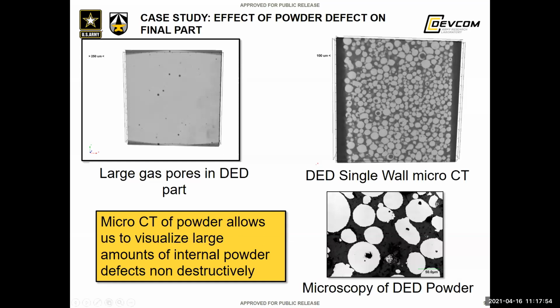So from microscopy, as you can see from this single image that I took when I did microscopy on this a few years ago, you're only seeing less than 20 particles at a time. Obviously, this is dependent on the magnification that you use, as well as the particle size of the powder itself. But from this, we can see there are some particles that have issues. However, it doesn't look like it's a great amount.